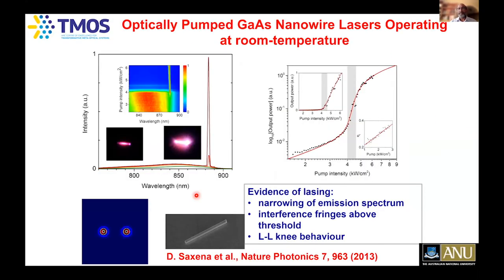To cut the long story short, based on the design of Dhruv Saxena and another student, Dr. Jenny Jiang, now at Cambridge University, she has grown these gallium arsenide, aluminum gallium arsenide core shell nanowires, which are about 260 nanometers in diameter and about 6 microns long. Then we transfer them onto a glass slide, pump them with the laser and look at the light coming out. Below threshold, you see a very broad light emission, like photoluminescence or spontaneous emission. Above threshold, you see a very sharp light emission, like a laser, coherent light coming out.